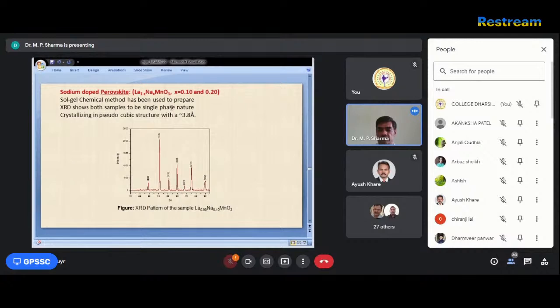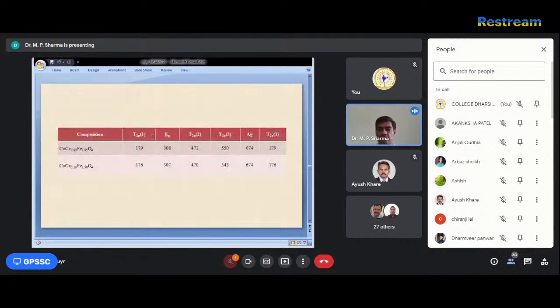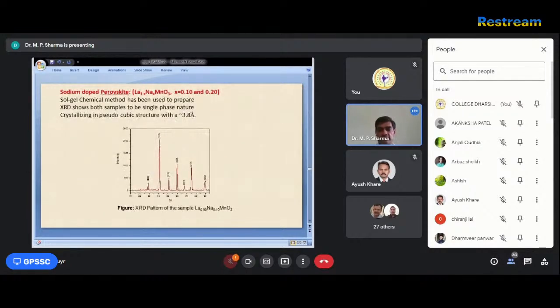When you check this, this is the XRD pattern of sodium 0.1. Okay, so this shows a purely crystalline nature, and the lattice parameter is given as 3.88 angstrom, and it is merely pseudo-cubic. Pseudo-cubic means it is another type of structure, but it is considered as pseudo-cubic. Pseudo-cubic means there is some alpha angle, so it is slightly tilted, like 89.9. So it is slightly distorted.